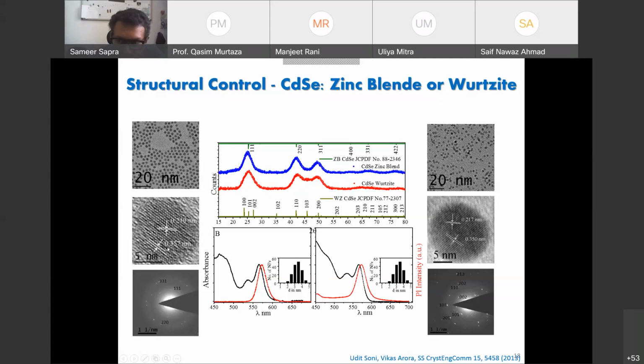So all these things, you see 0.357, and this is the wurtzite value, 0.350. You can actually match all these with the zinc blende or wurtzite phases. So the presence of 002 is definitely wurtzite. 111 is definitely zinc blende.